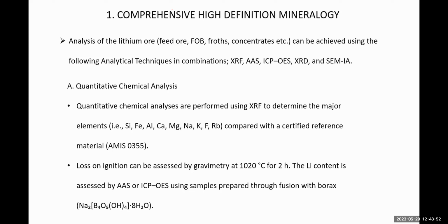The lithium content can be assessed through AAS or ICP. And please note this: any method that you use for the analysis of your lithium content must be a flame technique, meaning that the material has to be burnt and the atoms atomized, either through absorption or emission. You should have a detector that can detect through absorption or emission.